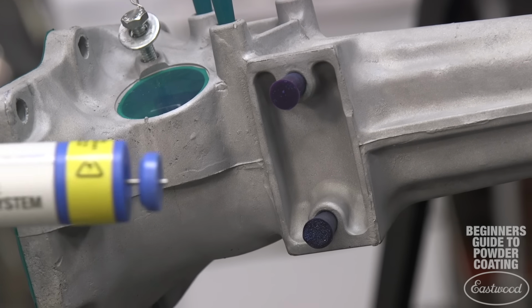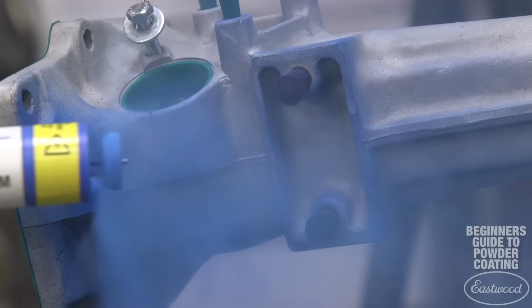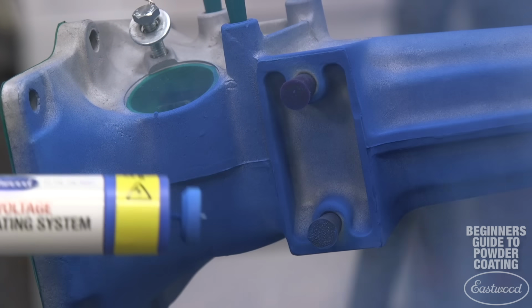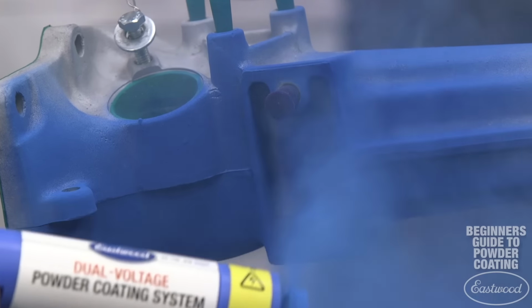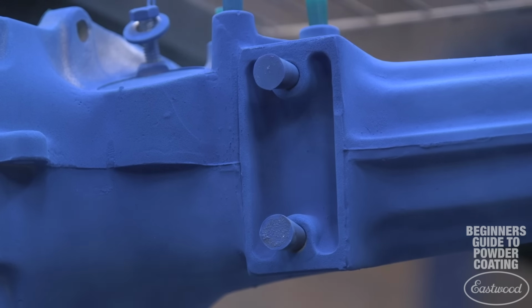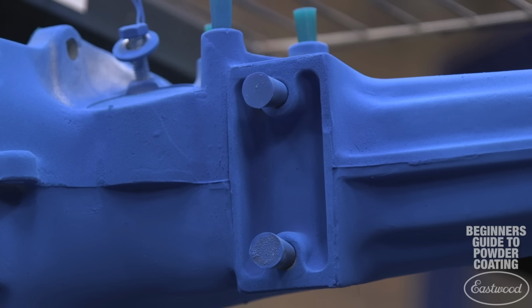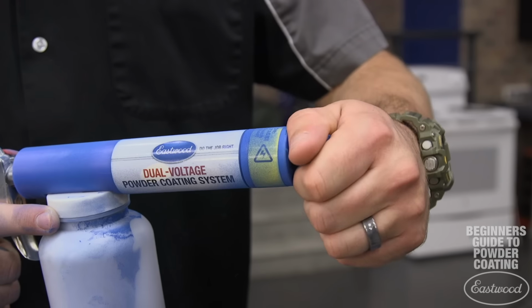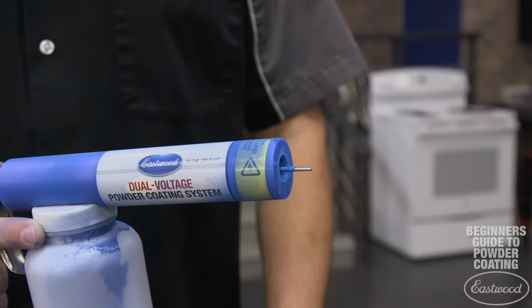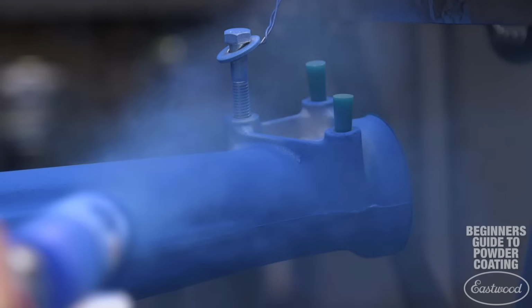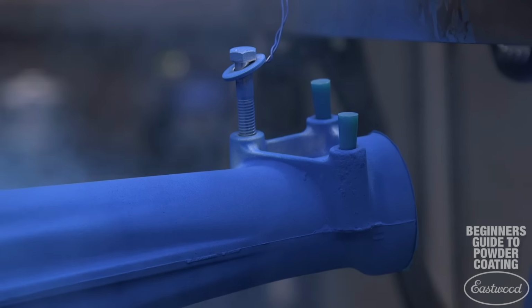Also, spray these areas first, because by spraying them first, you haven't built up as much of a charge, which will repel the powder. Start spraying the area with the gun parallel to the part, and the deflector will direct the powder out of the side and onto the part. Once you spray the tight areas, you can remove the deflector and switch the gun back to the higher voltage setting to spray the remaining larger areas.